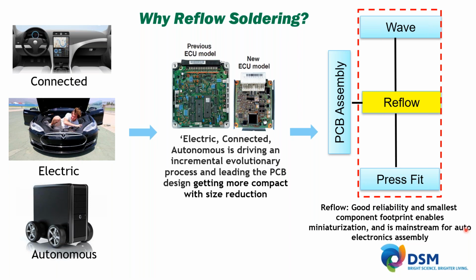And the reason for that is that surface mount devices are much smaller. So unlike the old wave soldering process, the reflow process lends itself to these much tinier electronics. And of course, with the demand in both consumer devices and automotive going to much smaller boards, much smaller space, much lighter products, miniaturization of electronics is important. The challenge that presents, of course, is now that connector, that thermoplastic that you've molded, needs to go through that heating process. So the metallic solder has to melt, but of course the device or connectors can't deform or melt as it goes through that heating process.